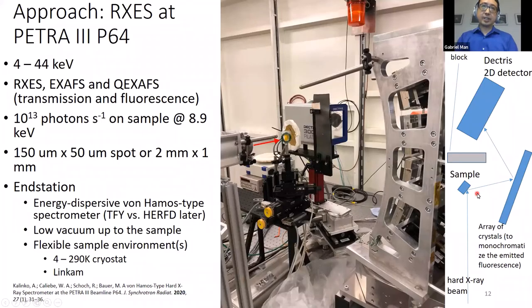So here's a slide on how the resonant X-ray emission spectroscopy work was done. It was done with the help of Dr. Alexander Kalinko at PETRA P64. This beamline is optimized for resonant X-ray emission, XAFS and quick XAFS. Has the ability to focus the spot, have at least two different spot sizes. We opted for the smaller one because that would improve the energy resolution that we would get from the spectrometer.